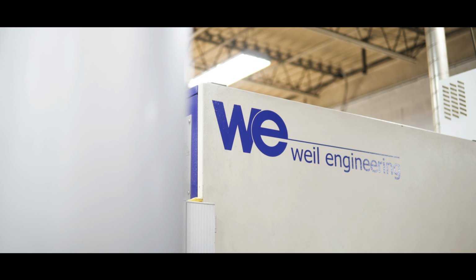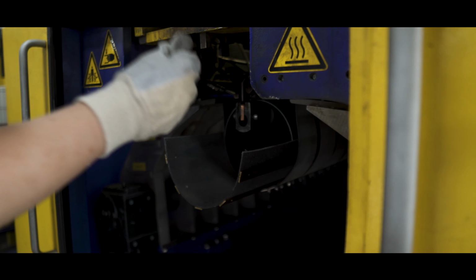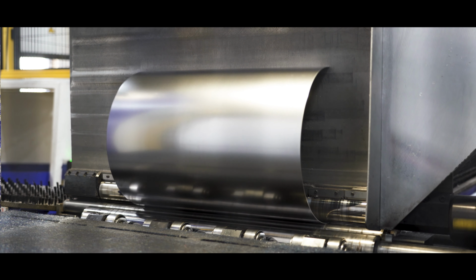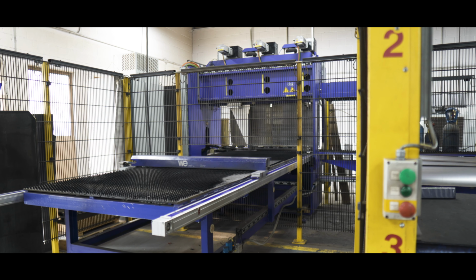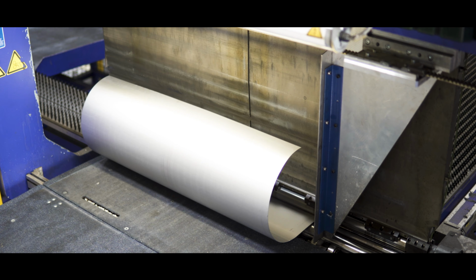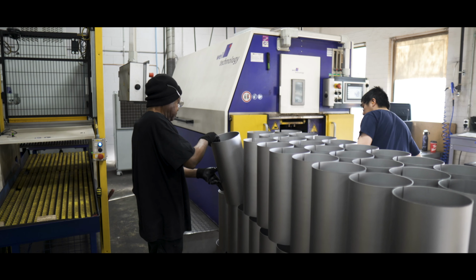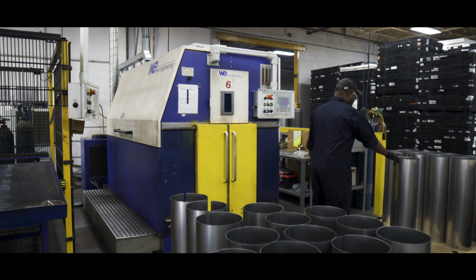What advantages did you see when you upgraded your original CO2 laser to a solid state laser? We find it to be a formable weld when you're finished with it, but also the ability to configure the FlexMasters the way we wanted to be able to do it. So in our case, we configure it with one multi-roller serving 2 FlexMasters. We're able to move the beam back and forth efficiently and maximize the uptime of the actual welding stage as the multi-roller outperforms a single FlexMaster. So in our case, we got a faster weld, we used a smaller footprint, we got a more formable weld, and easier to set up. So for us, it was a huge win.